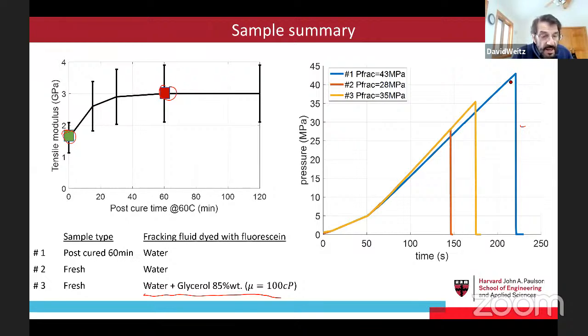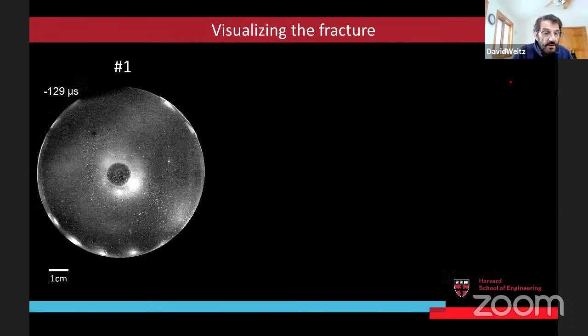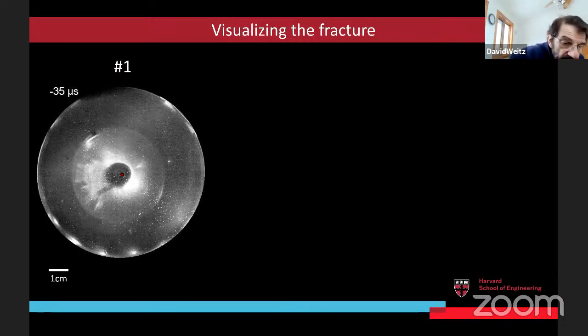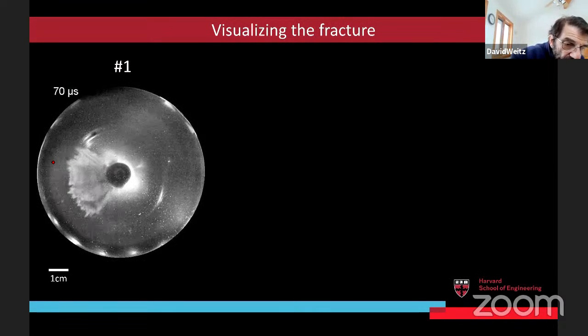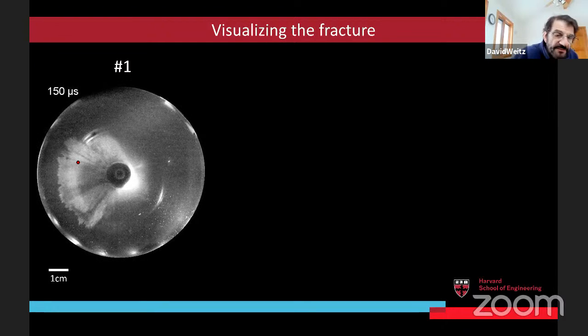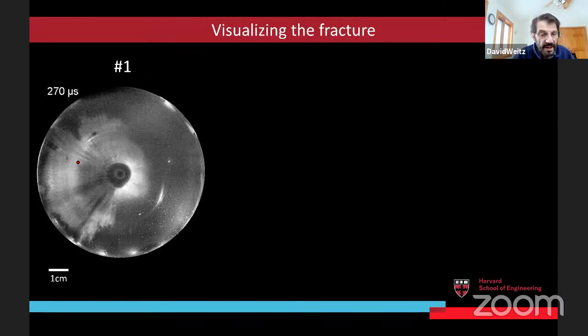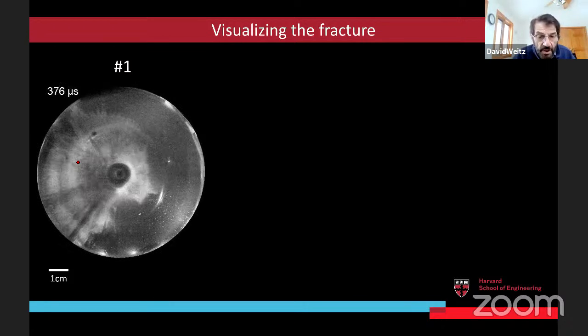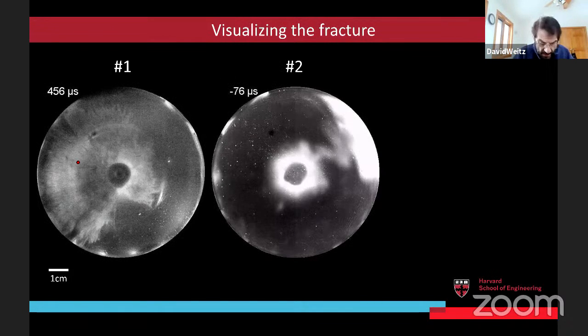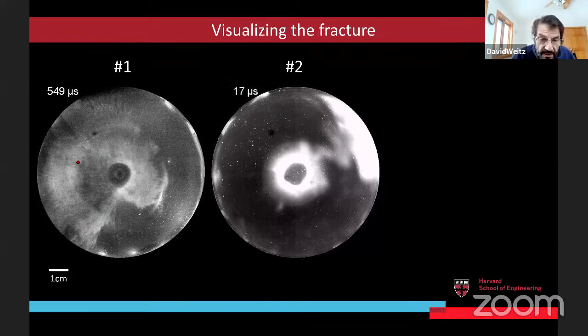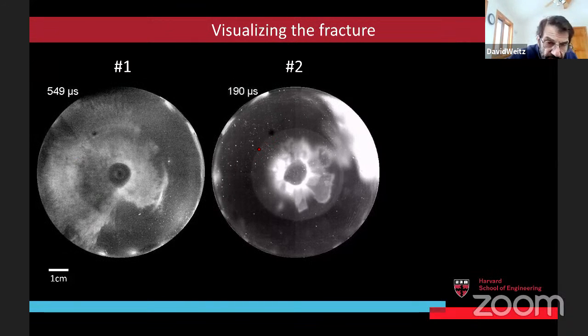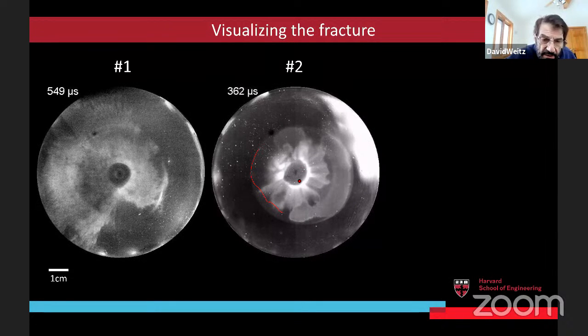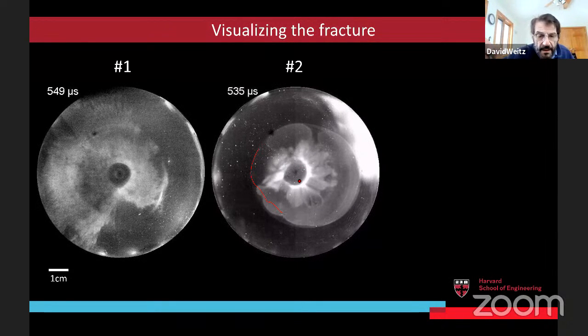This sample one is the stiffer sample. So it's been cured. It's a little bit more rigid. And we inject water in this, and you see that the fracture is way out in front, and the water is following this, and it eventually breaks itself all the way across. If you go to the one that's fresh and use water, in this case, you get something that's a little softer, and so now you get a fracture that doesn't break all the way across, and you can get this stick-slip motion. The water is catching up and pushing it in stick-slip.